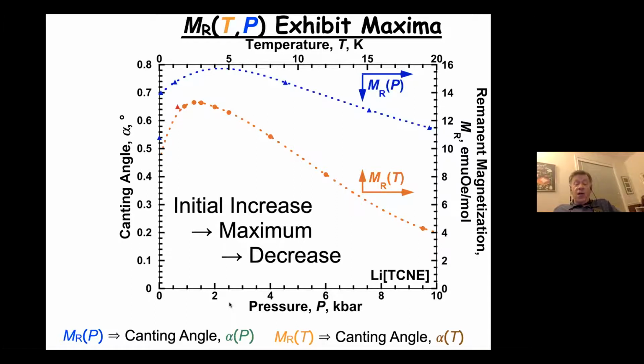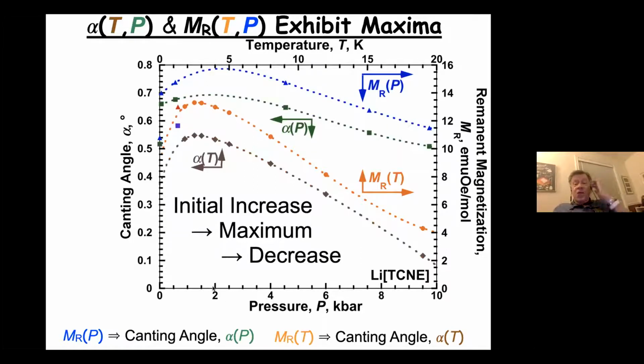And from this, of course, we can get the canting angle as a function of pressure and temperature. And that's illustrated in green as a function of pressure and illustrated in brown as a function of temperature. Note on top is the temperature scale and on bottom is the pressure scale. And they mimic, of course, the remnant magnetization from which they're derived, as you would expect. And you can see, again, it rises up, reaches a maximum, and then comes back down. So there's an unexpected, nonlinear, non-monotonic change of both the canting angle as a function of pressure as well as a function of temperature for this material. Now, to be honest with you, we don't know why.